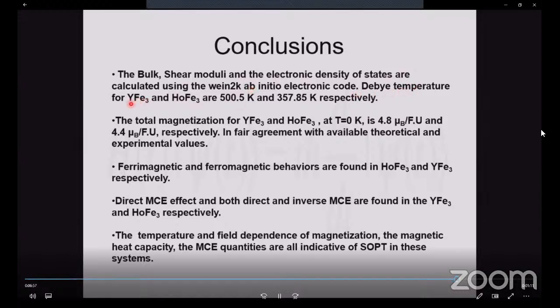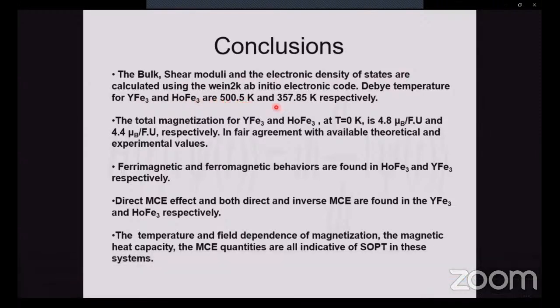The Debye temperatures of YFe3 and HoFe3 are 500.5 Kelvin and 357.85 Kelvin respectively. The total magnetization for YFe3 and HoFe3 at 0 Kelvin is 4.8 μB per formula unit and 4.4 μB per formula unit respectively, in fair agreement with available theoretical and experimental values.